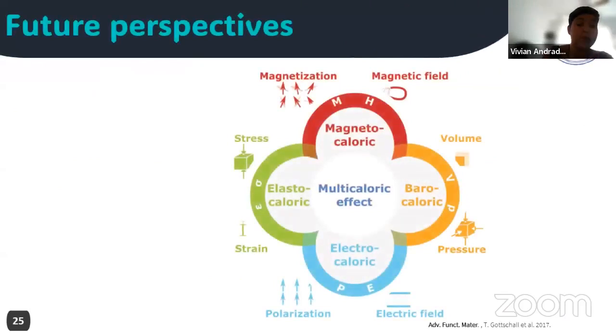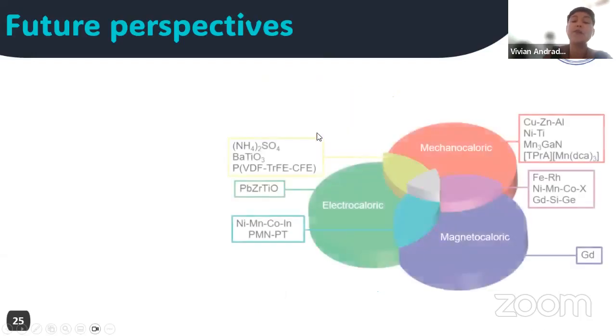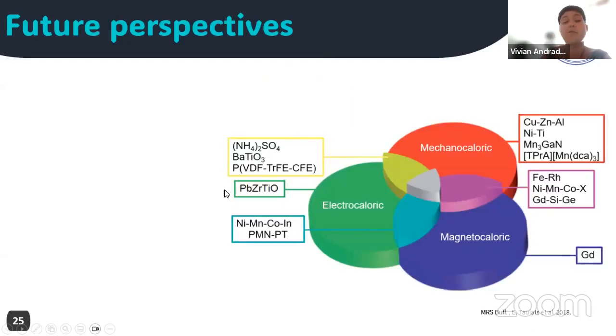In the future, we aim to use the multi-caloric effect, coupling the mechanocaloric effect with the electrocaloric and magnetocaloric effect. The types of materials evaluated in this type of system include, for instance, PVDF, a polymer, and Heusler alloys like nickel-manganese base, nickel-manganese-indium, nickel-manganese-gallium, and nickel-manganese-cobalt. We also have gadolinium-silicon-germanium, a material I've also worked with.